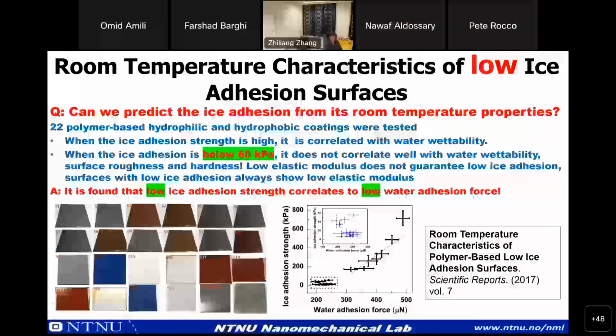However, low elastic modulus does not guarantee low ice adhesion. On the other hand, surfaces with low ice adhesion always have a low elastic modulus. So these are the correlations between room temperature properties and the low temperature properties.